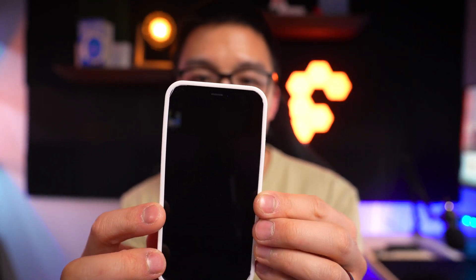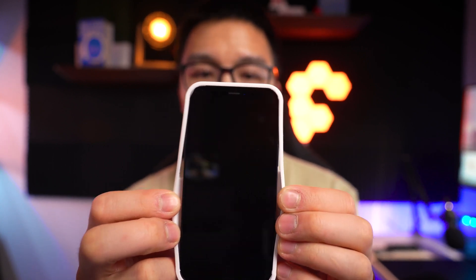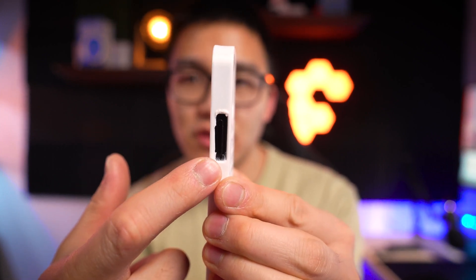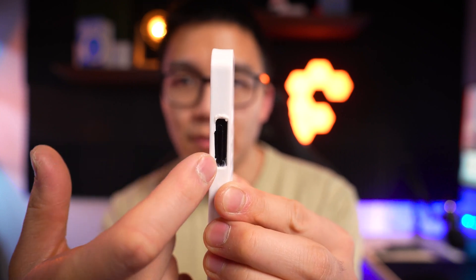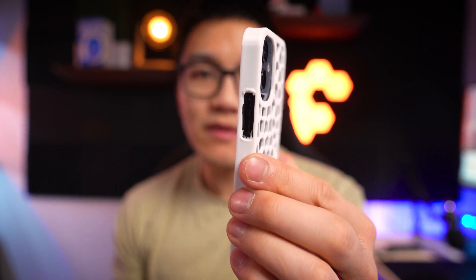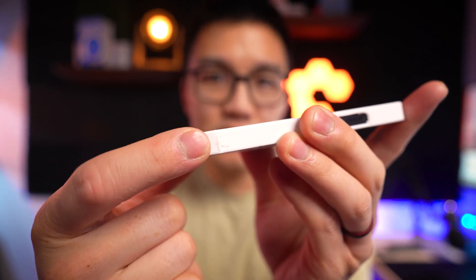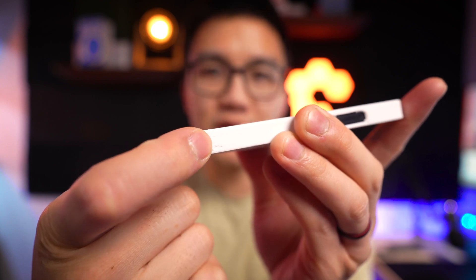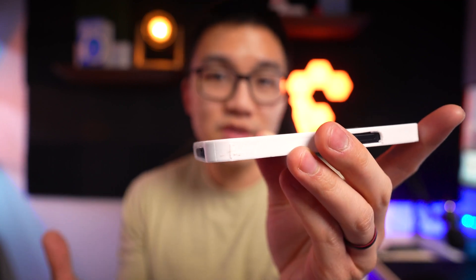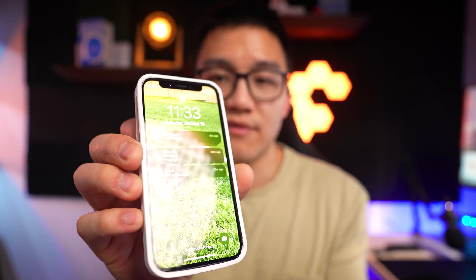One thing I don't really like about TPU is how flexible the sides are — it feels like the phone could drop out at any point. Looking at the sides, you can see some stringing at the very edges where the extruder jumped from one side to the other. Also, bridging is not the best for TPU, so if you're planning to print anything with overhangs, be aware you're going to get some stringing and it won't be super clean. On the sides there are some blobs sticking out that you can't really clean off with a knife cleanly, but after cleanup it looks pretty decent overall.